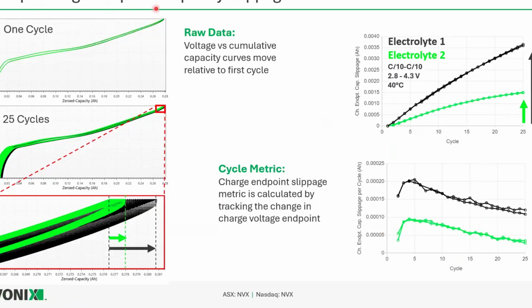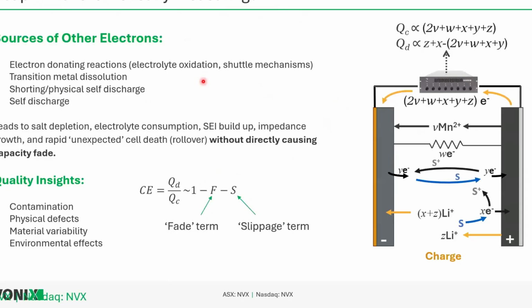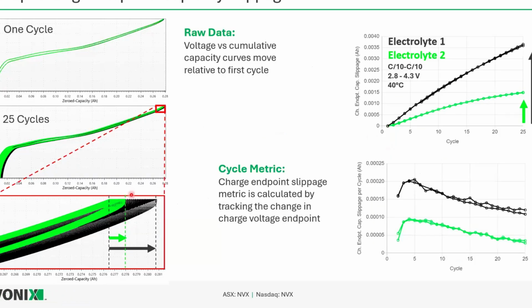And just to talk about slippage a little bit and how we turn this into a cycling metric, we can picture this as if we're counting more electrons during charge than we do during discharge because of these electrons we overcount due to these mechanisms like this short circuit here. We have to put in more charge during charge to get the cell charged, and then during discharge we don't count as much charge because there is self-discharge happening in the cell. We're always going to have this shorter discharge than our charge cycle.